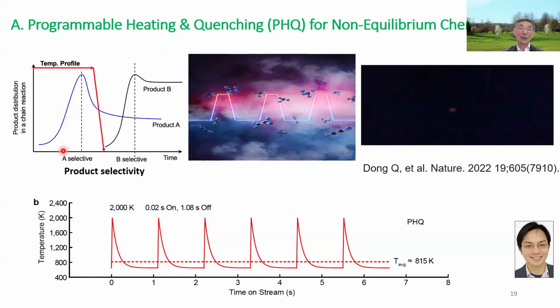For plastics, if you have a long pyrolysis time, thermodynamic equilibrium will tell you it will be hydrogen and soot or coke. But if you want to produce ethylene or acetylene, you don't want equilibrium, you want to cut off. For example, you have a high temperature and cut off immediately, and you can form acetylene. This was a hypothesis around 2020. So can we demonstrate experimentally that this kind of non-equilibrium, simple heating can increase the selectivity and yield?